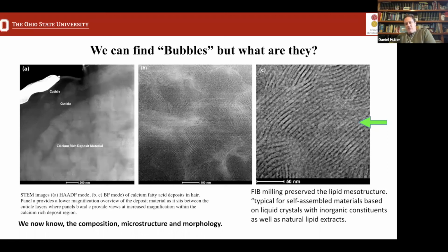So this was a really good example. We talk a lot of times about the gallium ions coming down and doing damage into the specimen and what their interaction might be. And here we've got a case of very sensitive material. The lipids and proteins that make up hair would be very sensitive to the beam exposure. And here we're able to produce a very thin specimen and also preserve this liquid crystal mesostructure within the fatty acid.